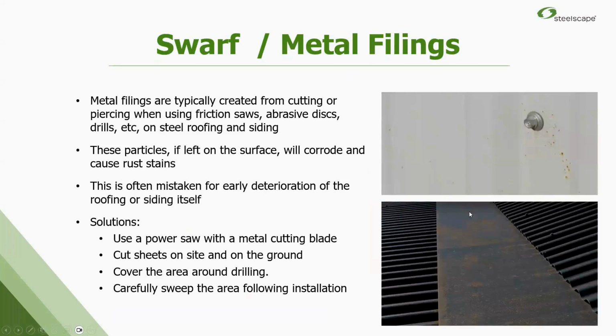Swarf and metal filings. Sometimes they have to cut panels on site and then you're drilling in, and you get little metal shavings that come off and land on the painted surface. If you don't clean those up, they start to rust. And the call comes in as my paint system's failing. And it's like, no, that's something sitting on the surface that's rusting. Doesn't cause too many long-term performance issues, but it looks terrible. I mean, this one on the bottom is awful. And this is a brand new installation that looks like this. And once that red rust stain is on there, it's almost impossible to get off. Usually I have to come in and field paint or replace the panels.